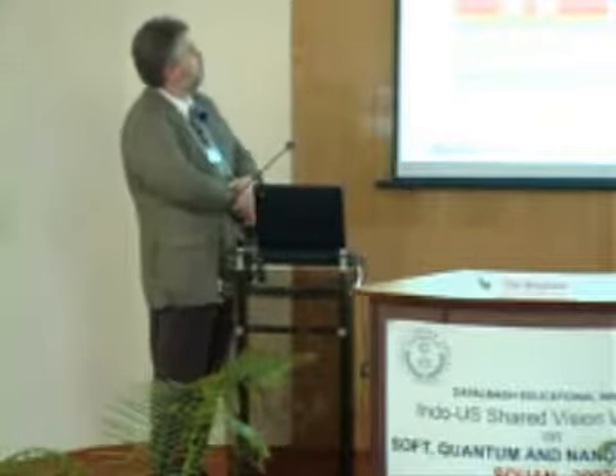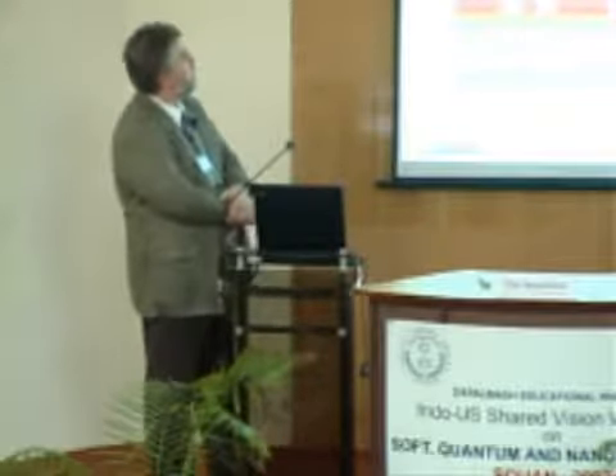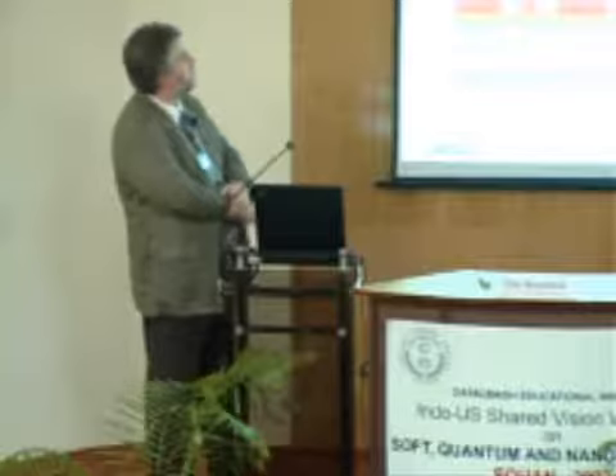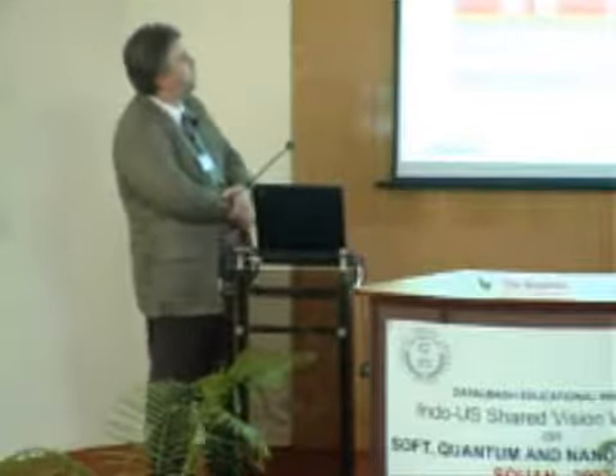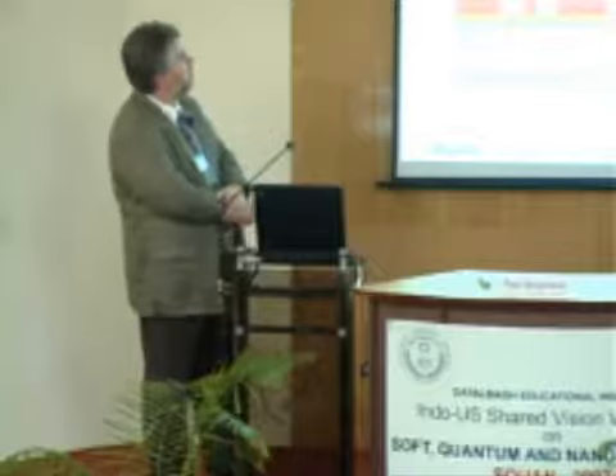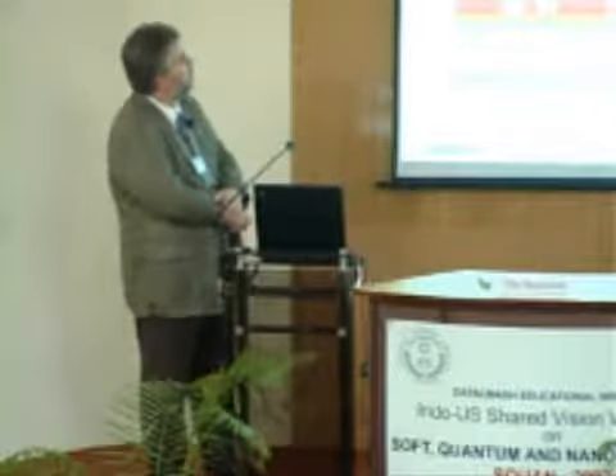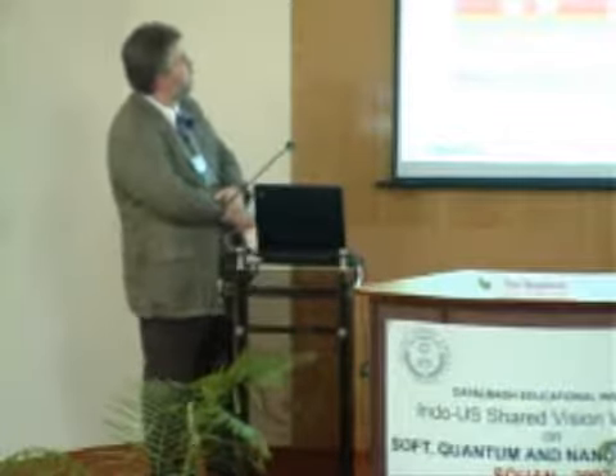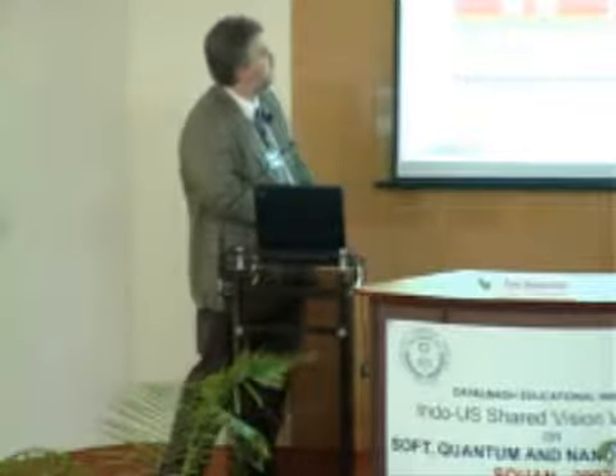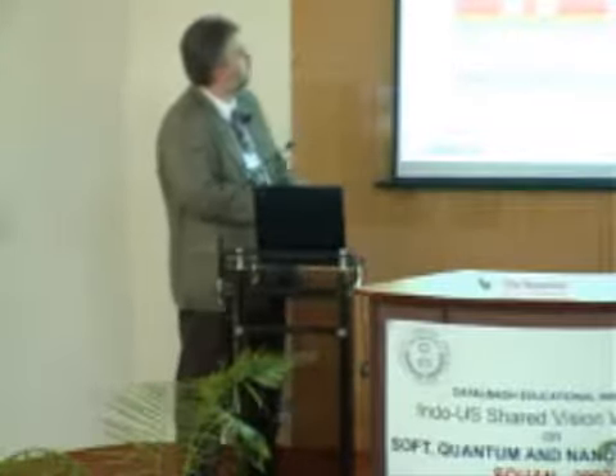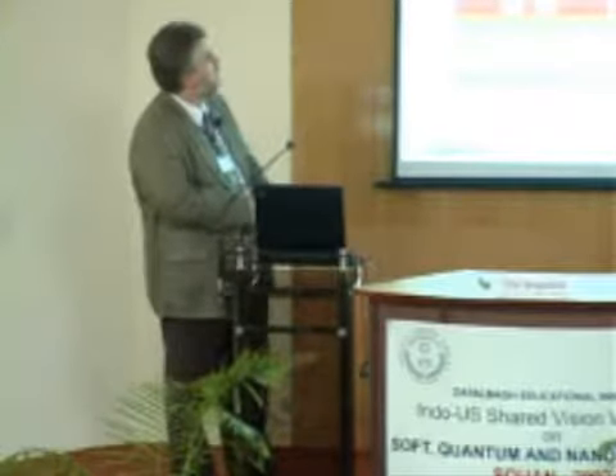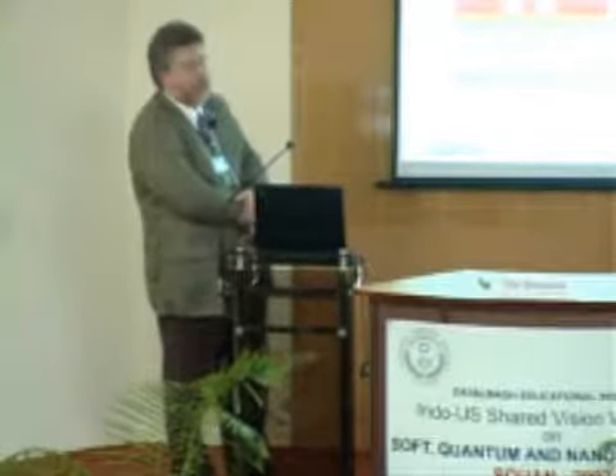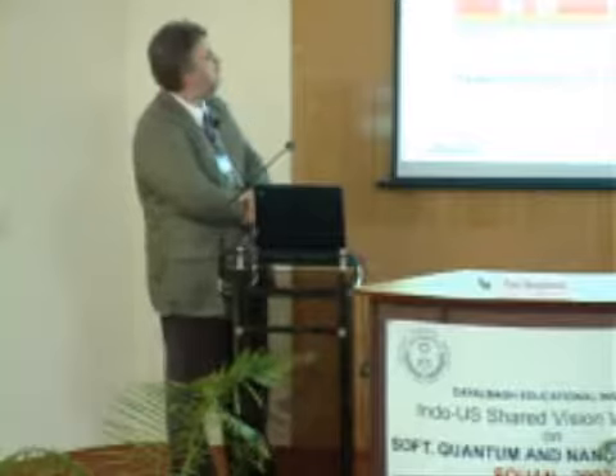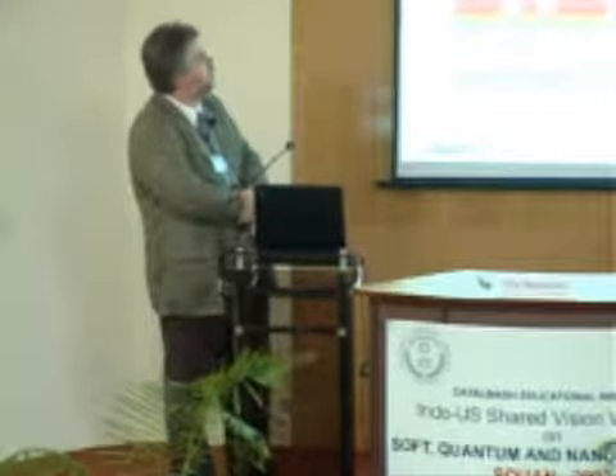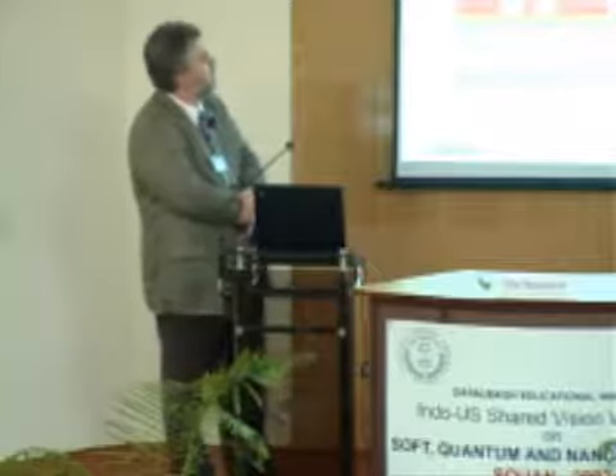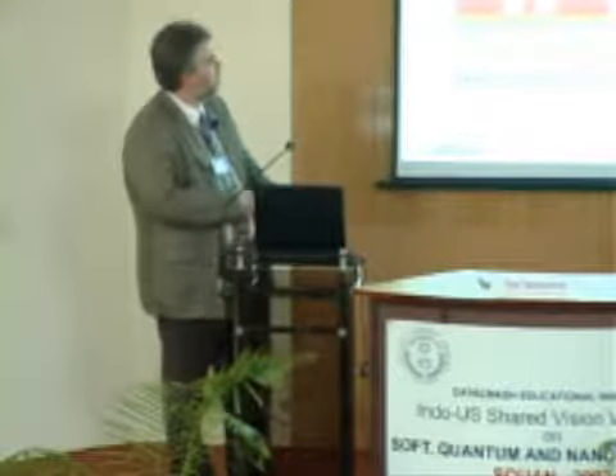So a typical process flow would be to produce a suitable isolation, some sort of a substrate, and produce an appropriate material for electrons and quantum dots. In the case of the work that we have been pursuing, we've been looking at metallic dots and metallic electrodes. So we started out looking at the aluminum oxide and the nickel magnesium oxide systems.